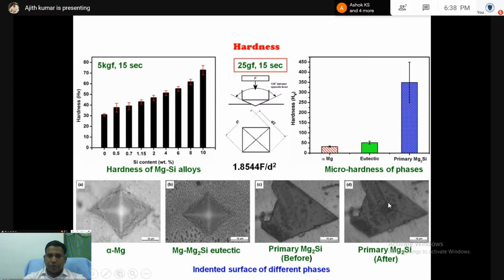kind of indentation mark. At all the corners, we can see some cracks. This is because this material is highly brittle. Due to that brittleness, when you indent on the particular face, it cracks like glass. So from this analysis, we can understand that due to the indentation mark, the breaking is happening. This is because of the highly brittle Mg2Si particles.